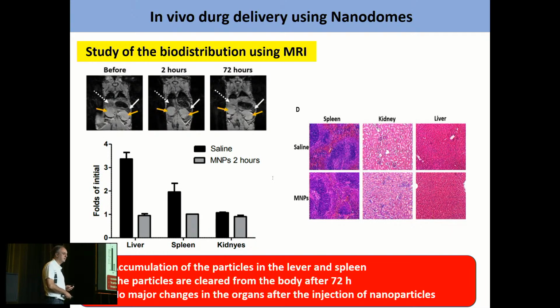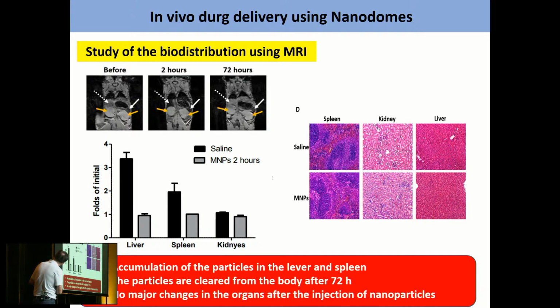And then we studied the biodistribution using MRI. And you can see here we have the liver, the spleen, and the kidneys. And you can see here that the ones become black, meaning that the particles go to that area. And here I show you quantification. The signal decreases, which means that the particles have gone to that area, meaning that the particles concentrate in the liver mainly, and also in the spleen, but they don't go to the kidneys.